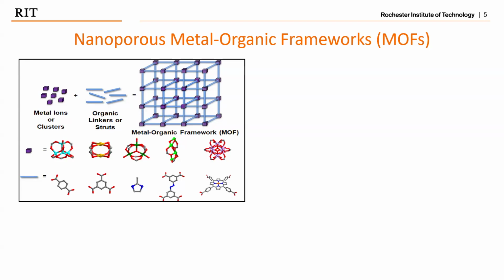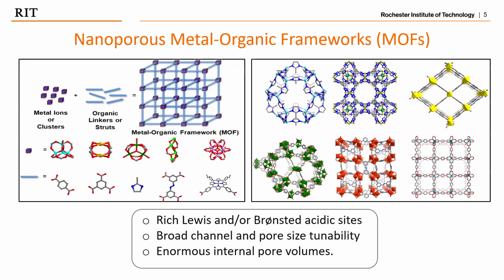Actually, people use metal organic frameworks a lot for gas storage. The reason is that they have a decent amount of Lewis and Brønsted acidity sites, either open metal sites or protons exposed on the node, and they also have broad pore size and pore volume.